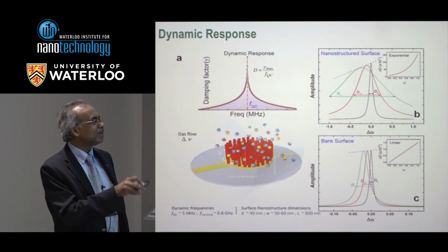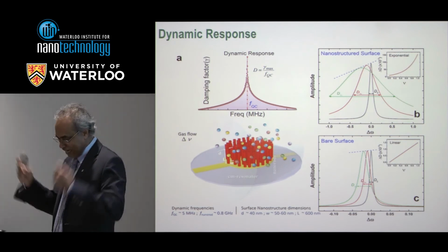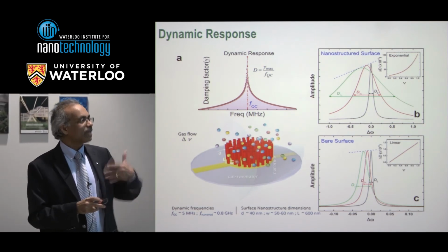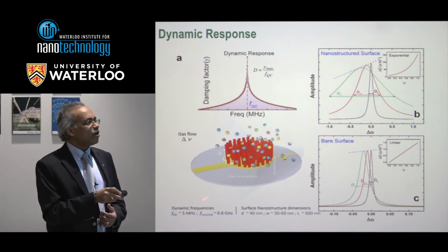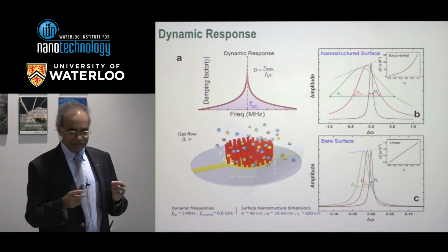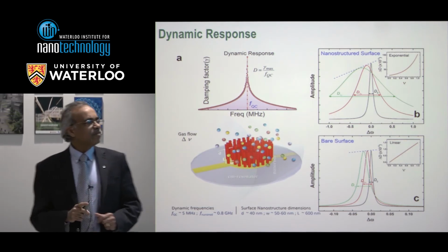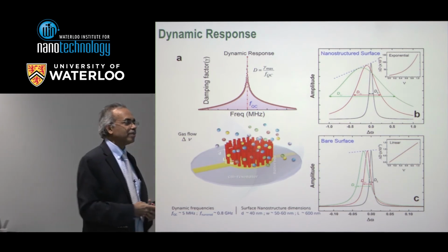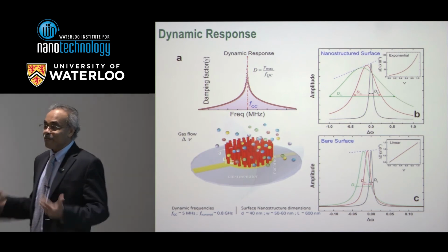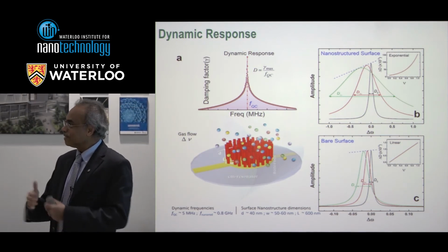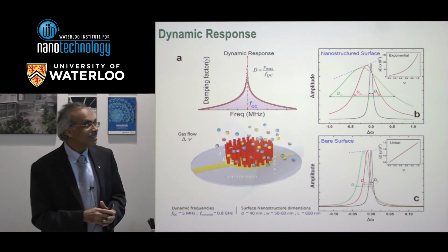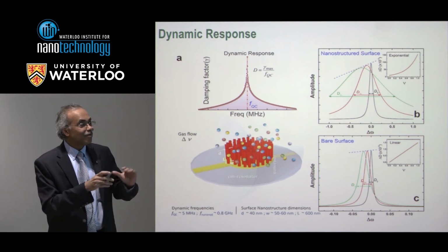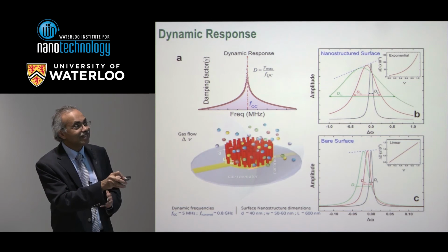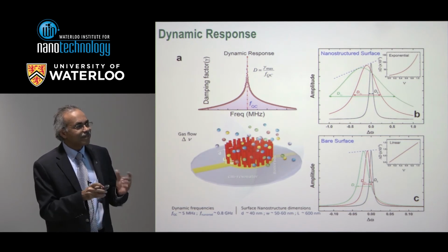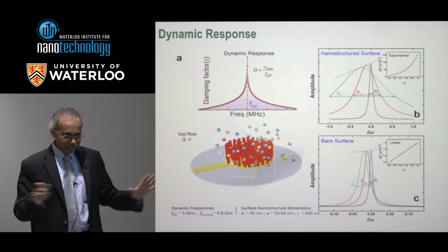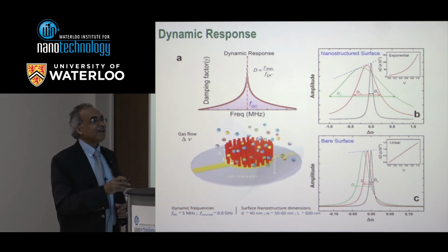If you put nanotubes or nano pillars or nano rods on the surface of the cantilever or a resonating structure, and provided the distance between these nano rods is equal to the mean free path, which is around 60-70 nanometers in air, immediately Stokes' law is no longer valid. It's interesting. Stokes never said it is valid at nanoscale. It can do amazing things if you go to nanoscale devices and modify the surface with nanostructures, where the distance between them should be around the mean free path. And then a very interesting effect.